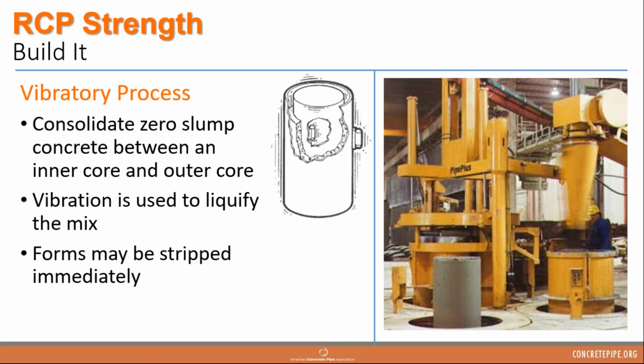If we take a closer look at the vibratory process, again, we're using that zero slump dry mix concrete, but rather than a rotating roller head inside the forms that create the inner wall, we're actually using a vibrating inner core, and that helps to consolidate the concrete. The vibrators within the inner core and also on the outside of the jacket provide the exact energy needed to liquefy the mix, which allows concrete to consolidate. Now, I know when I say liquefy a dry mix of concrete, that sounds crazy, but we have a video to illustrate that that we'll jump to next.